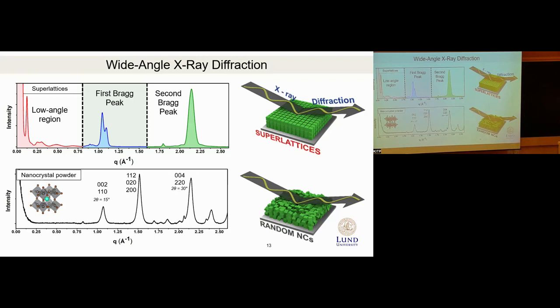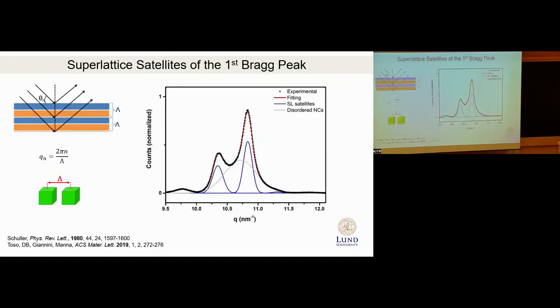What about the two different lattice parameters you see in the first Bragg peak? So, yes, I'll explain where this comes from. Because often, in the early works, this has been interpreted as an orthorhombic splitting of the lattice constant. But if you do a simple Bragg analysis, you will conclude that your particles should be like 100 nanometers to see two orthorhombic reflections. Well, in this case, these are nanocrystals, so there is an inconsistency. And the reason is that the origin of this structure is a superlattice origin, essentially. And what I mean by that is the following.